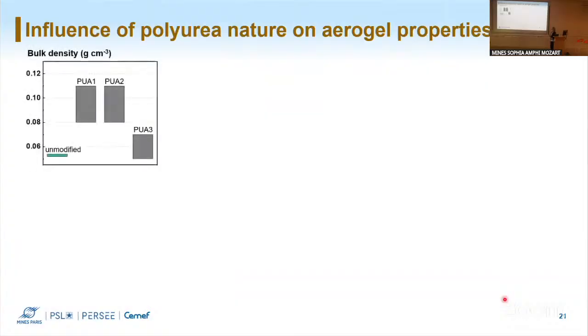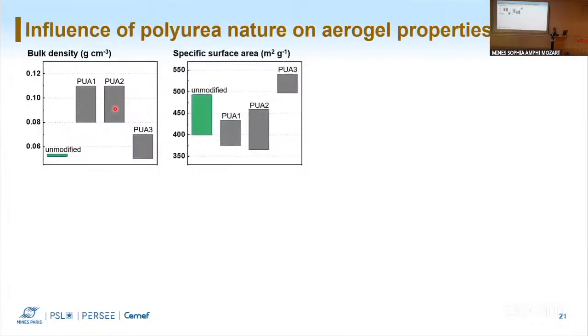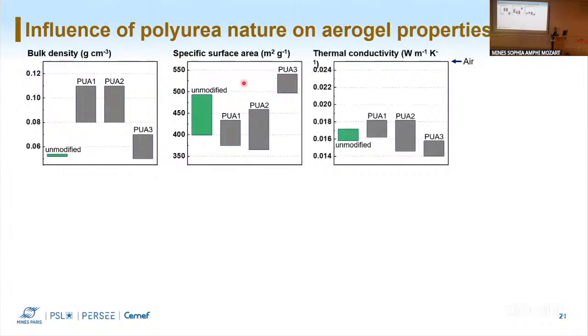Let's see first the influence of polyurea nature on our materials. We can see that the bulk density was low for all materials, but it was higher for the first and second type of polyurea used. Then the specific surface area decreased from the neat materials to the first and second type of polyurea. However, it stayed always in higher values for the third type of polyurea. The thermal conductivity was not really affected, so we see that the values are very close to the ones of the neat pectin aerogels, and we are satisfied with this.